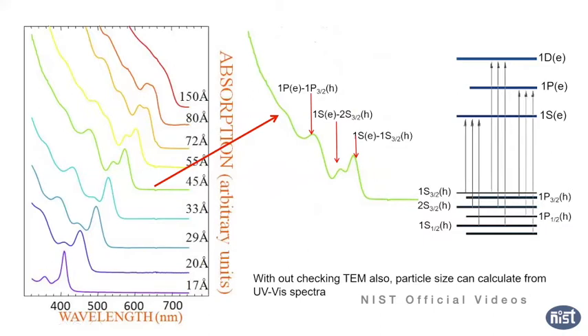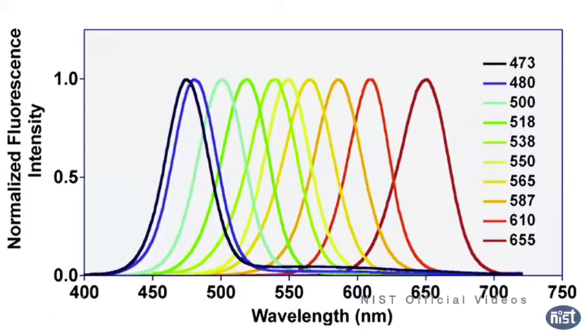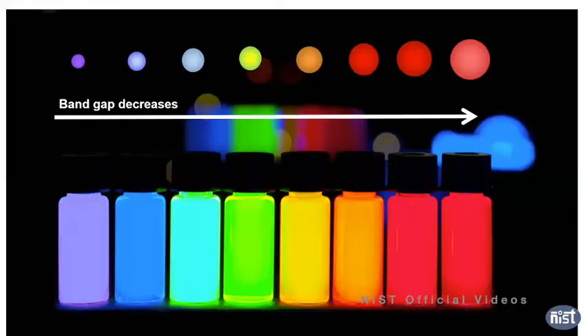And when you take the emission, you can see the emission changes from blue to red, just changing the particle size, nothing else. You do not need to change anything, you just do the synthesis a little bit longer and collect the sample at different times, and you can see the different sizes of particles, and the emission is nicely distributed. So that reflects your nanocrystal size also. And you can see in the vial how it looks.